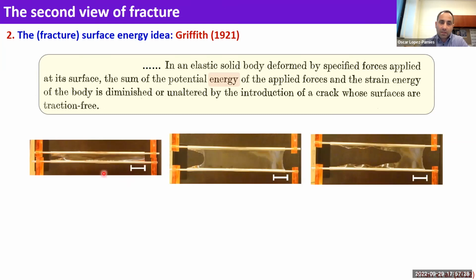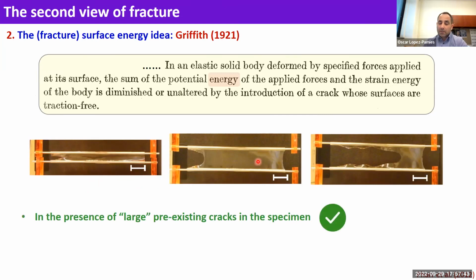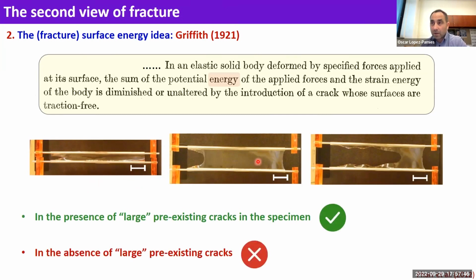Think of a tape that you are going to cut with scissors, and therefore put in a crack. This is a very singular feature, geometrically speaking. And when you pull on it, at some point, the crack is going to run. And Griffith explains this. So this is great, except that it's not so great, because it's not explaining the previous case that I showed you about strength, right? If you apply a force to a piece of material, let's say tension, it does not follow this. Fracture will not happen according to Griffith, it would happen according to strength.